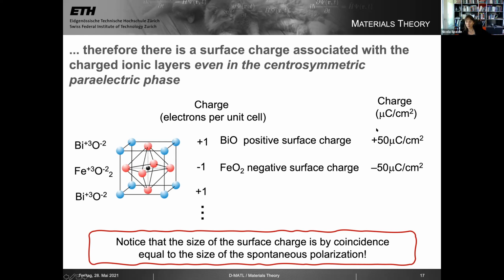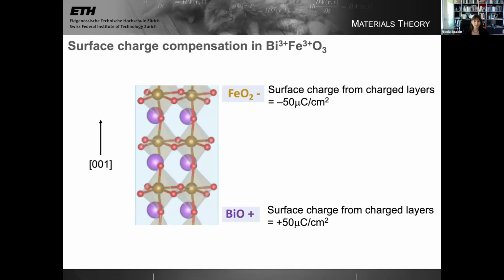So again, just to recap, this surface charge is coming just from the way that the atoms are layered. It's there in the centrosymmetric phase. It's nothing to do with the ferroelectricity. But then we have, in addition to that, a surface charge that comes from the ferroelectricity. Of course, in practice, they're both there, but we can, as a thought experiment, decompose them into these two contributions.